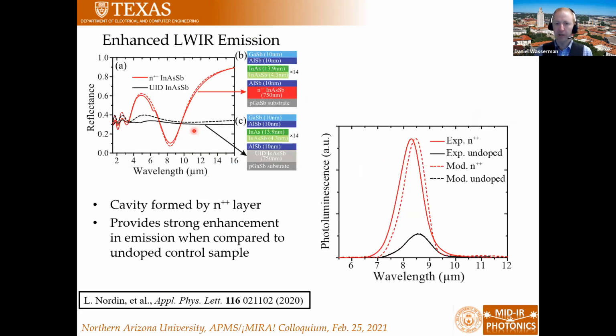And so in this case, what I'm showing here in the upper left-hand corner is the reflection from these devices. So what we have is an N++, this is our heavily doped plasmonic ground plane. And then above that, we grow a thin superlattice designed for a band edge of approximately 10 microns, 9.5, 10 microns. And we grow a control sample that is the exact same structure, but with an undoped ground plane. Right, so this is just a dielectric. It's not a plasmonic material.